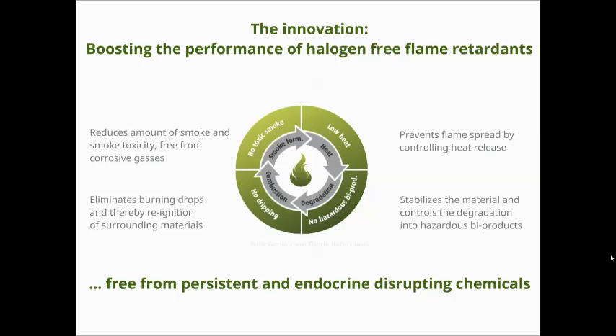We can also see that we eliminate burning drops, and that's a big part in this sort of reignition of materials. The most visual example that most people can relate to is a curtain that burns and drops, and then it ignites the carpet, and then it goes on from there. And finally, we're also talking about smoke and smoke toxicity. So we are completely free from corrosive gases. Carbon dioxide and carbon monoxide are things that come from the burning of the plastic itself, but at least we can get rid of the other stuff, so to say. So it's a big improvement in smoke toxicity as well. And as you see, it's free from persistent and endocrine disrupting chemicals.